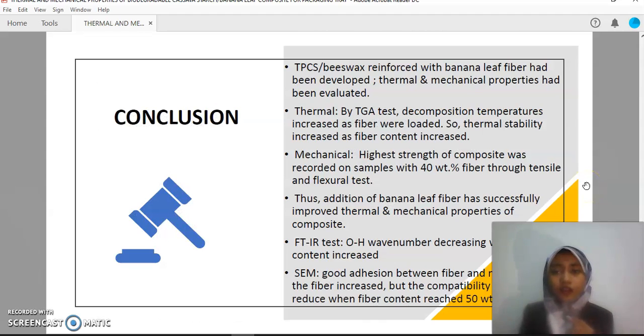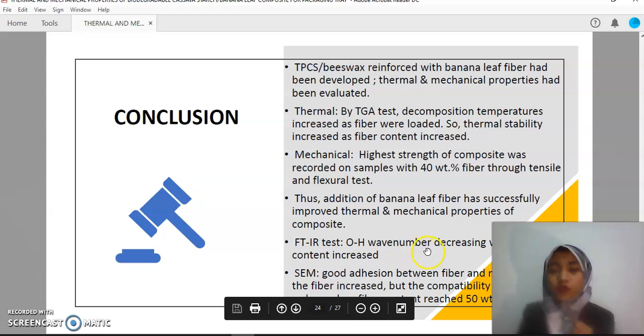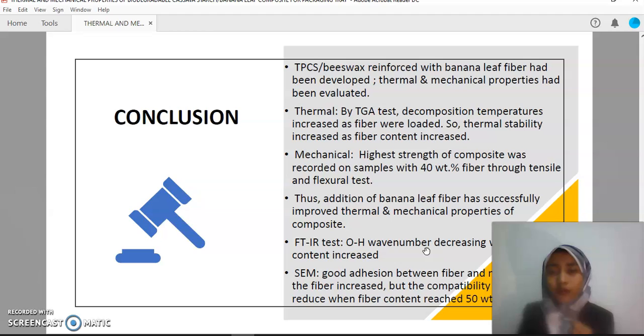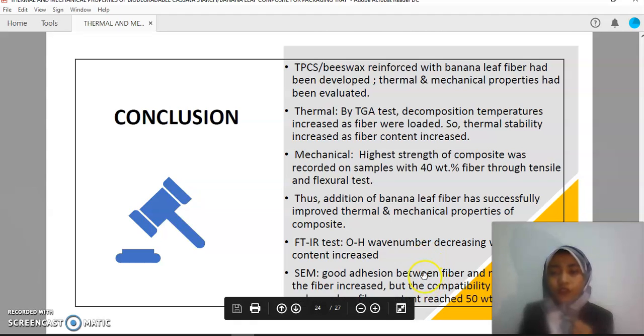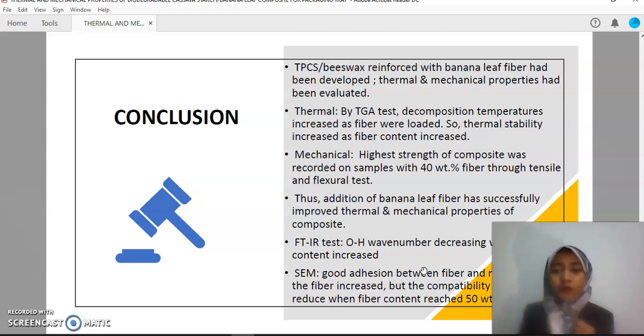So the conclusion is, by the TGA test, the thermal stability increases when the fiber content increases. The highest mechanical strength was observed at 40% fiber through the tensile and flexural tests. So we know that mechanical properties also increase with the addition of banana leaf fiber. For the FTIR test, the OH wave number decreases when fiber content increases, which helps to increase the mechanical properties. And for SEM, there is good adhesion between fiber and matrix when the fiber increases. It also supports the tensile test and the thermal testing. So we know that 40% is the optimum fiber content to be used in the composite.